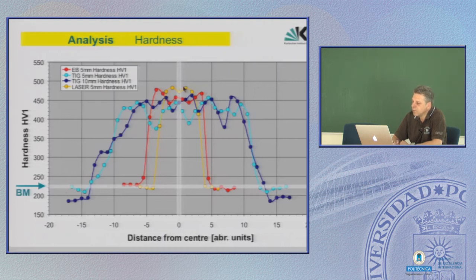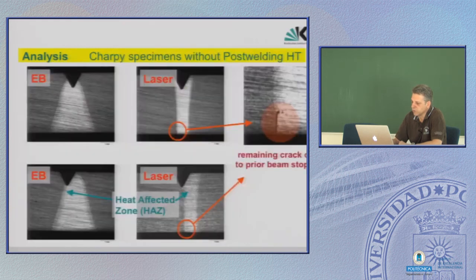In the middle of the beam or thick welds, we have very high, very hard material, and at the end, you see, especially in the thick welds, there is even a much softer material, or much softer variant of Eurofer. And that's all due to the temperature distribution over the weld surface or the cross-section.